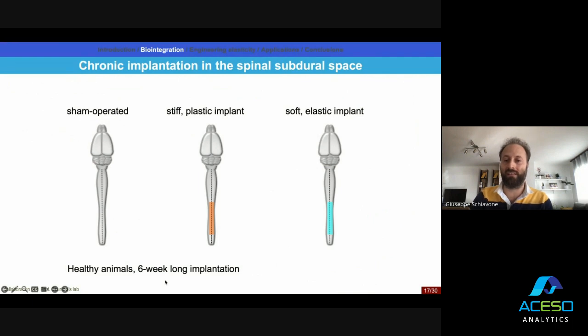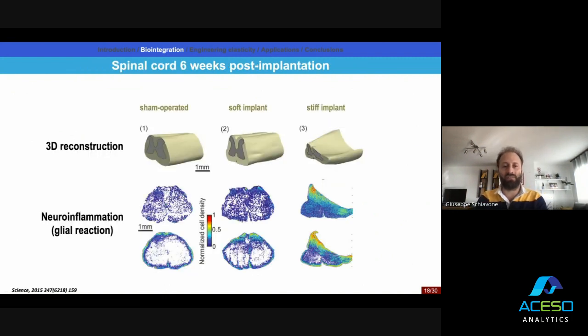The devices were kept in for 6 weeks, and then the animals were sacrificed, and then we looked at the tissue response in these three groups. And these were the results. So if you see the 3D reconstructions in the sham operated, so the animals that received the surgical procedures but no implantation, you see that the tissue stays healthy and intact. In the center group, you see the soft implant device, so the device that we wanted to test. And you see that the tissue reconstruction looks very similar to the sham operated, meaning that the device did not affect significantly the tissue that we wanted to work with. And the third group, so the stiff implant, the population that received a rigid device in the spinal cord, suffered from significant deformation of the tissue, which then causes a lot of problems, locomotion impairment, and not only. So this convinced us that, yeah, this is the way to go. We need to use soft materials.